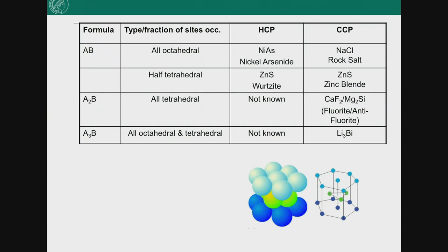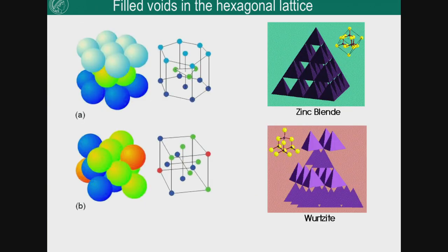it's the so-called nickel arsenide structure, or the sodium chloride, the rock salt structure. Here's mercury telluride, the zinc blende. There is also a hexagonal version of the zinc blende. But in hexagonal, we cannot fill all the tetrahedral sites because they come too close to each other, so the filling is more difficult. Therefore, we also know more cubic structures. Okay, so this is simply the zinc blende, and the wurtzite is again only a different stacking of the